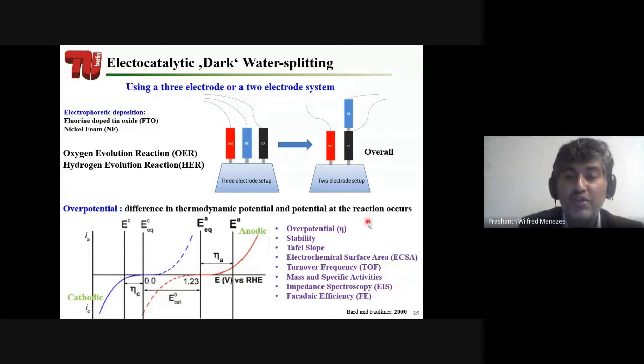In addition to overpotential, there are some other factors. As I already told you, stability is very, very important: how long the system can be stable. And then we have something like Tafel slope, which determines the efficiency of the reaction, how fast the kinetics is. Then we have electrochemical surface area, how much active surface is on the film. And then we have turnover frequency, how much we can produce in which reaction time.